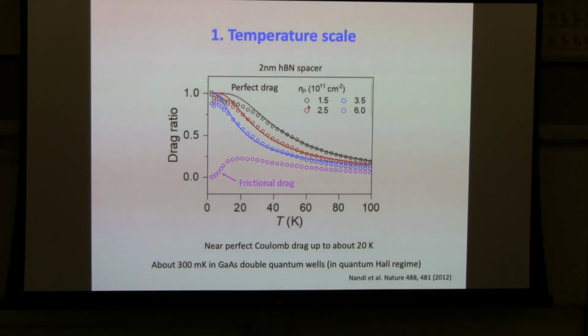At low enough exciton density, you can actually see that the perfect Coulomb drag lasts up to about 20 Kelvin in the system. So it's a reasonably high temperature scale, especially if you compare to similar experiments in the quantum Hall regime performed in gallium arsenide double quantum wells. The perfect Coulomb drag is only observed below 300 milli-K. So it's about 2 orders of magnitude higher in energy scale compared to this double layer quantum well regime.